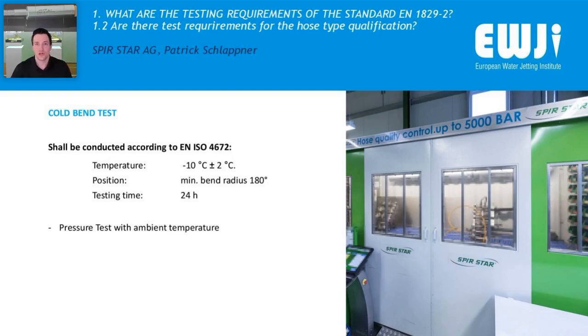We also do a cold bend test, and this is also specified in EN ISO 4672. Here, the hose has to be tested with a temperature of minus 10 degrees Celsius plus or minus 2 degrees Celsius. During the test, the hose has to be tested with the minimum bend radius of about 180 degrees. The testing time here is 24 hours.